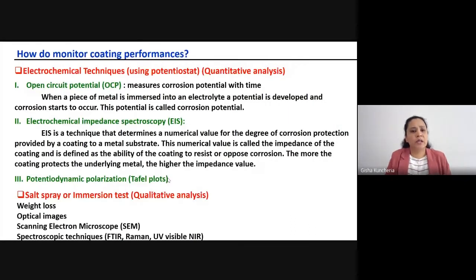Now, how can we monitor the coating performance? Coating performance we can analyze by either qualitative techniques or quantitative analysis. Quantitative methods are electrochemical, because corrosion is an electrochemical process. So these are electrochemical techniques using a potentiostat. The very basic technique is open circuit potential. What is open circuit potential? It's nothing. When a metal comes in contact with any electrolyte or any solvent, the metal develops a potential. That is the corrosion potential. So that potential we can directly measure using the potentiostat. That is the open circuit potential.